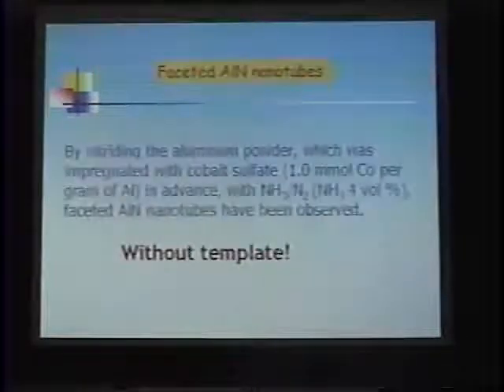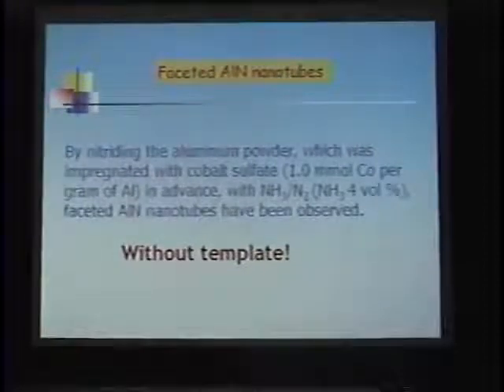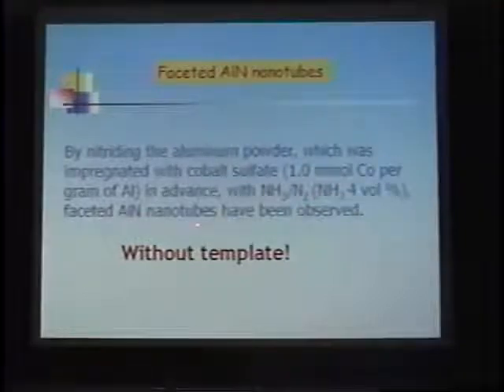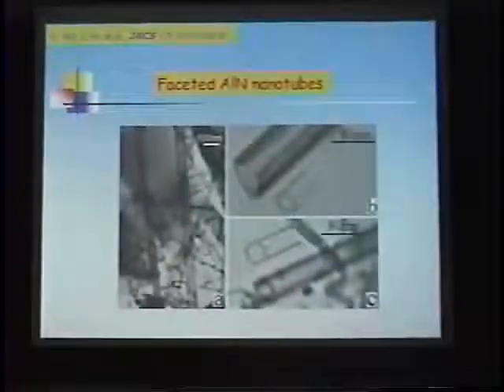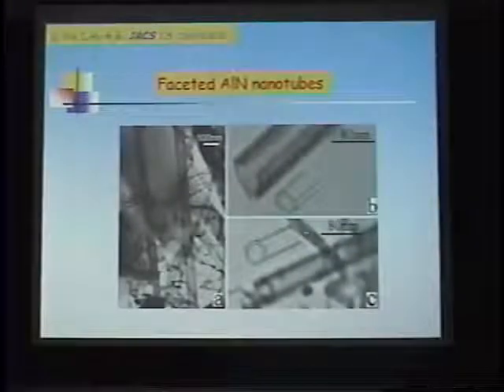And in our synthesis, a very simple synthesis, by nitriding aluminum powder with an ammonia and nitrogen mixture, faceted aluminum nitride nanotubes have been obtained. It should be noticed that we made this experiment without a template, so it could reflect the crystal habits of aluminum nitride itself. And here are some characterization results.